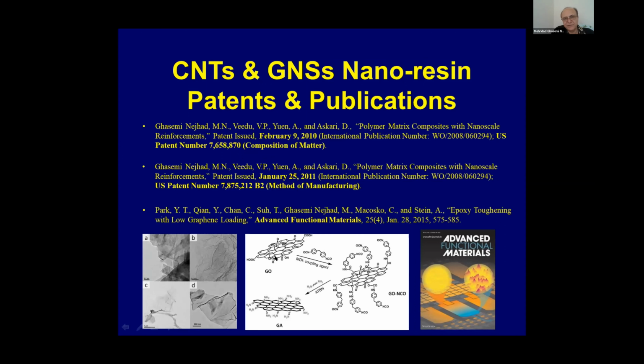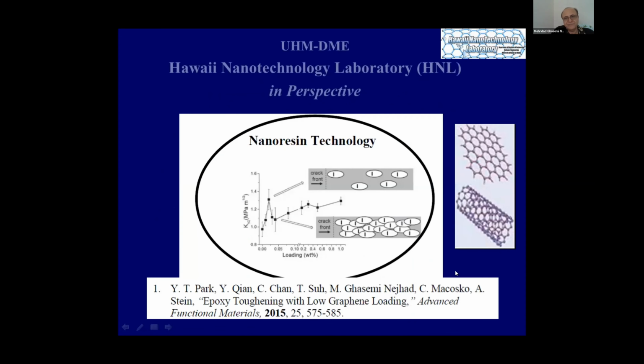graphene oxide, which has a hydroxyl and carboxyl group, and then we functionalize it with MDI group, so you get this GO-NCO molecular structure, and then we functionalize it with an amino group, and then eventually we get a graphene with the amino group functionalization that worked the best for the nanoresin that we had.